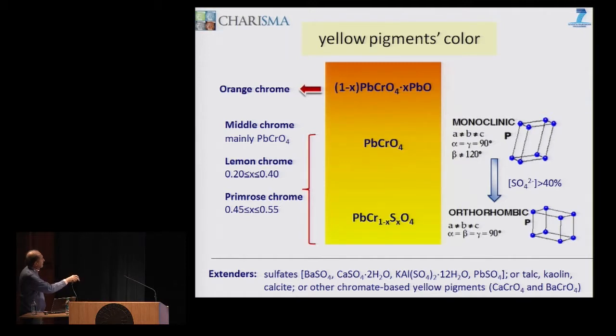can have different tonalities from orange to light yellow, and the different tonalities correspond to different compositions and also to different crystalline systems. Orange chrome is a co-precipitate of lead chromate and lead oxide pigment, and the middle chrome is pure lead chromate, in this yellow, but you have very white tonalities in the case of a co-precipitate of lead chromate and lead sulfate together to create a solid solution.